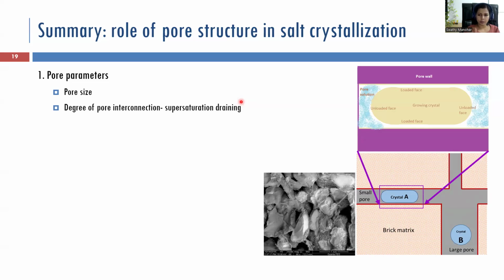Even if you have smaller pores in the system, if they are well connected with a larger pore, supersaturation draining would occur and the crystal would always have preferential precipitation in the larger pore. Again, if it's precipitating in larger pores, you will not have any damage.